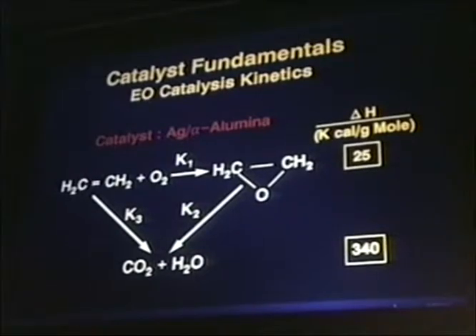As you can see, the important kinetics in this reaction involve not hundreds of reactions that some folks were talking about in the last day or so. Very importantly, it's just three reactions: K1 for the formation of ethylene oxide, K2 for the combustion of ethylene oxide, and K3 for the combustion of ethylene. As you may know, the combustion reaction, and very much should be, is very exothermic, by about an order of magnitude, from 25 kcal for the synthesis to about 340 kcal for the combustion reactions, plus or minus a few depending on EO or ethylene.